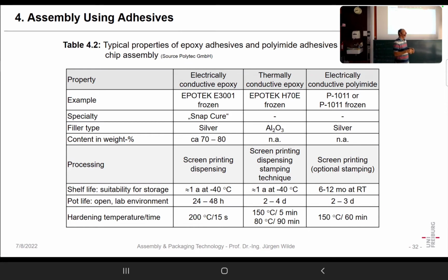215 seconds. As a rule of thumb, if you would take such a starting value, for a not snap cure, but for a normal epoxy, when you lower the temperature by 10 degrees, you roughly need to double the hardening times. So here again, for snap cure, below a certain temperature, nothing will happen. But for a normal epoxy that is not snap cure, you have that rule, 10 degrees doubles or halves the reaction rate.